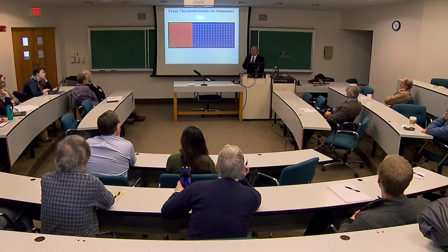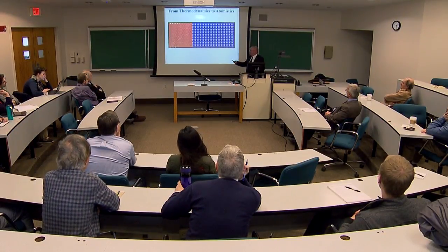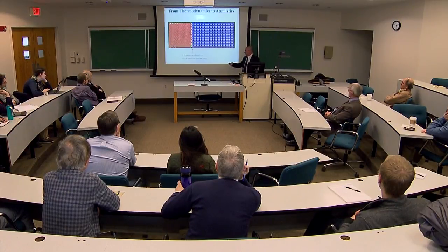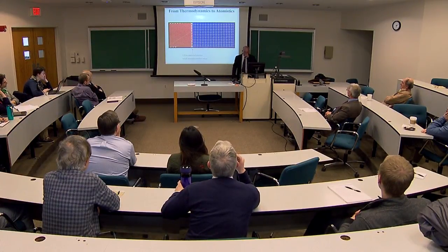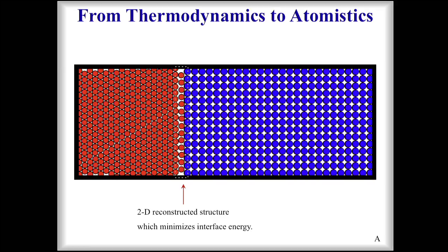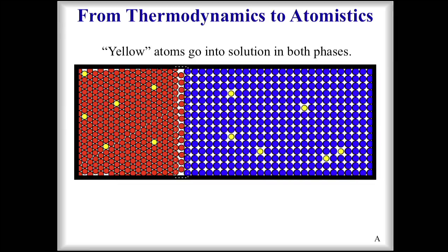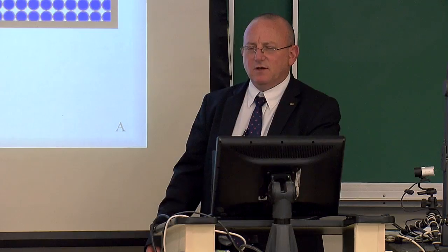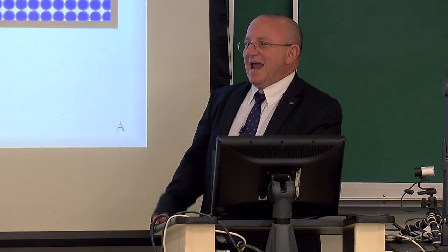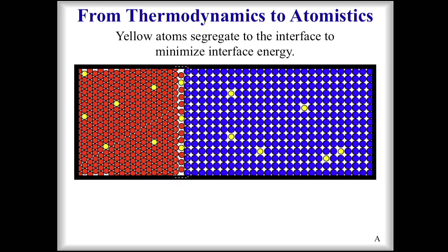If I do wait and I reach equilibrium, it's quite possible that the structure at this interface will change. This is called reconstruction, and I'll talk a little bit more about that later. This two-dimensional symmetry along that interface has changed in order to minimize the interface energy. That's a first-order transition by definition. Now I can add some yellow into solution, maybe a little bit more in one than the other because they're two different materials, but of course the chemical potential must be the same if I'm at equilibrium. And if the yellow going to the interface reduces the interface energy, then as I reach equilibrium, I will have some excess at this interface. And I can go through with my microscope and measure the number of yellow atoms per nanometer squared.